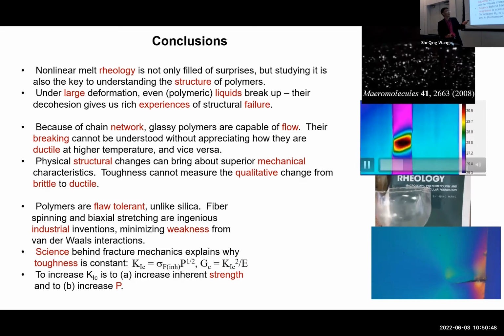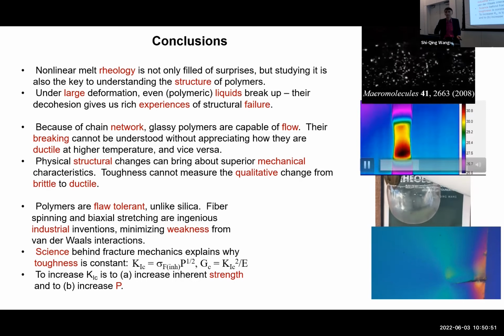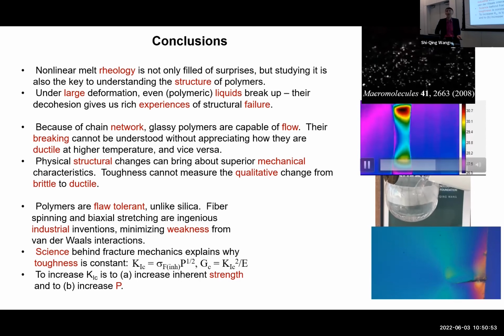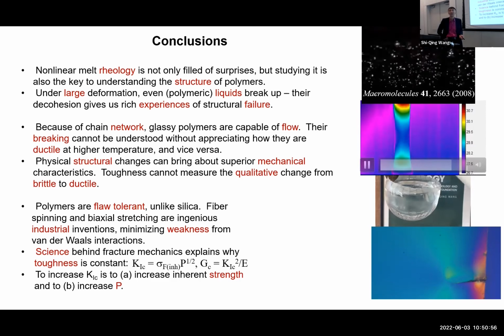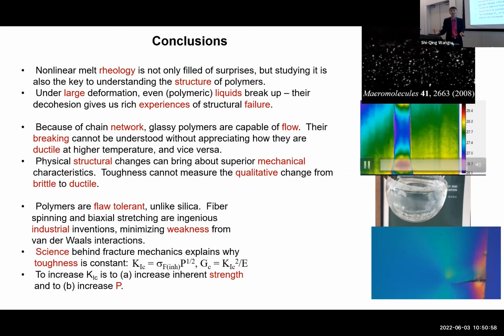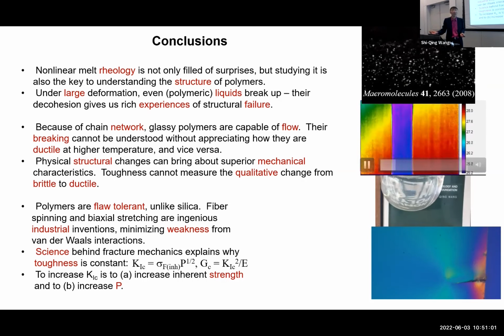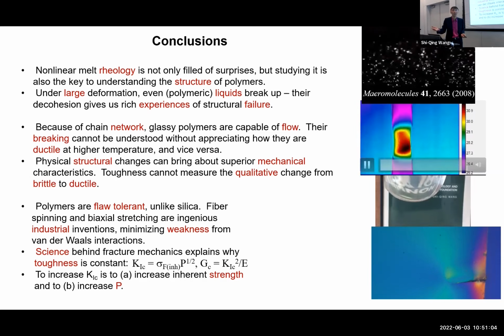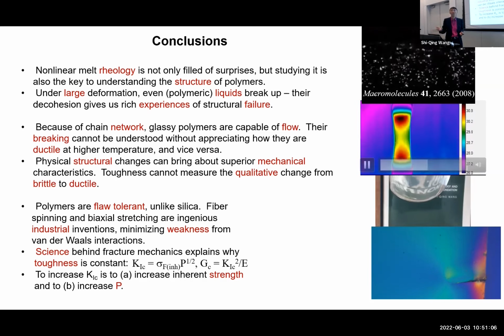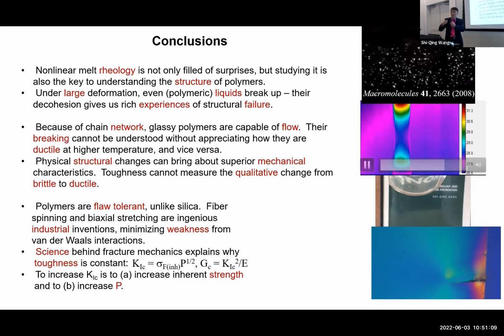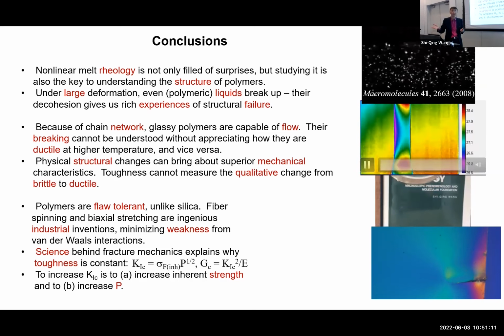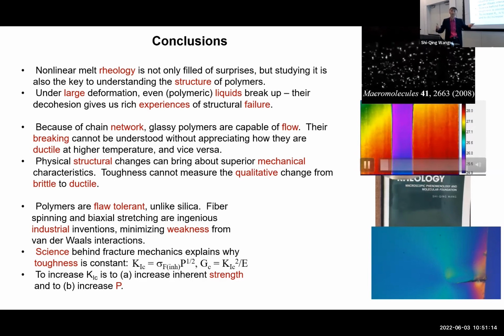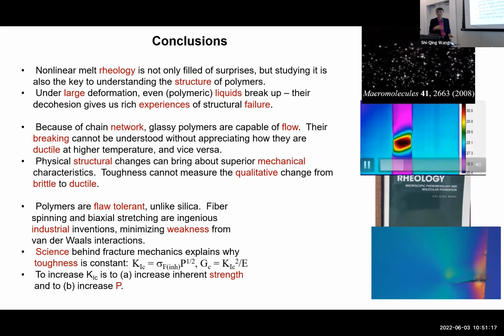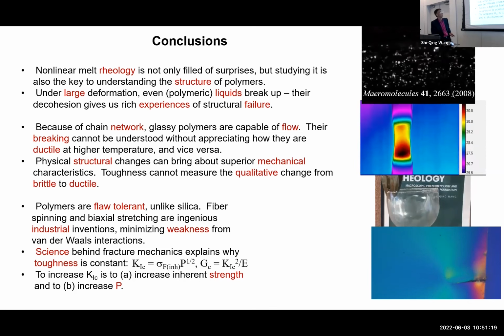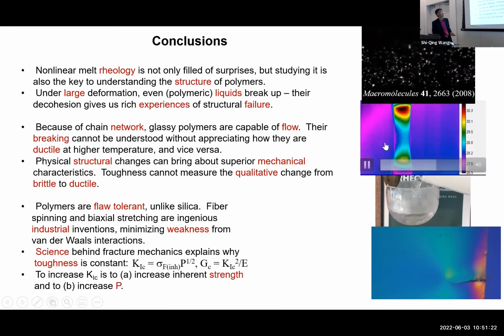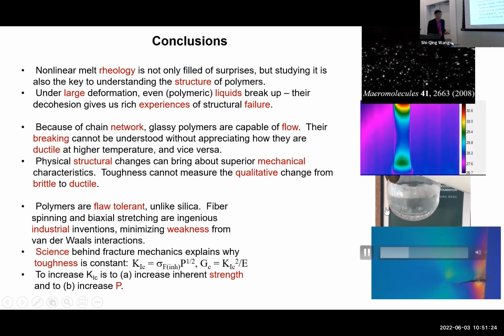And then the glassy problem is really a difficult one, because Eyring's idea doesn't work. Eyring says, give me stress, the barrier will always be lowered. Then if you follow that argument, your polymer will never be brittle. You can always yield. So it turns out the structure is what gives you the stress so that you can yield. If your structure, which is the chain network, breaks apart, then you cannot yield. That's my theory for the brittle-ductile problem. And then this is, of course, a beautiful example of showing the processing-structure-property relationship.